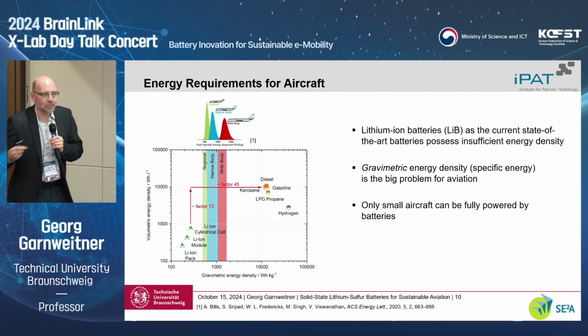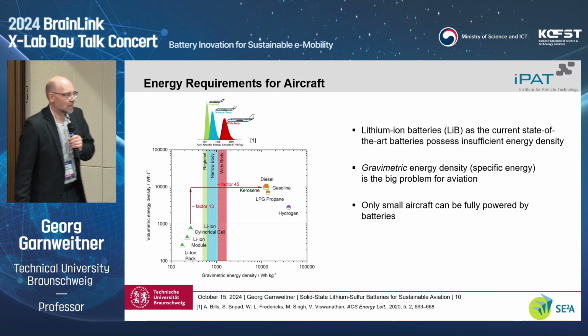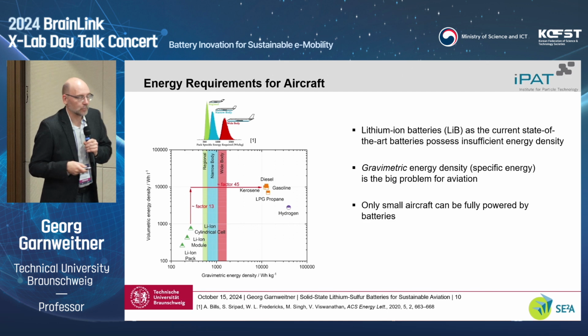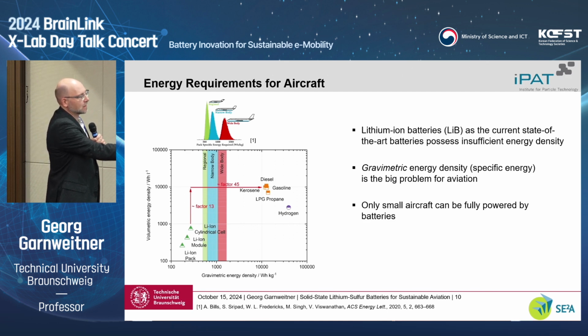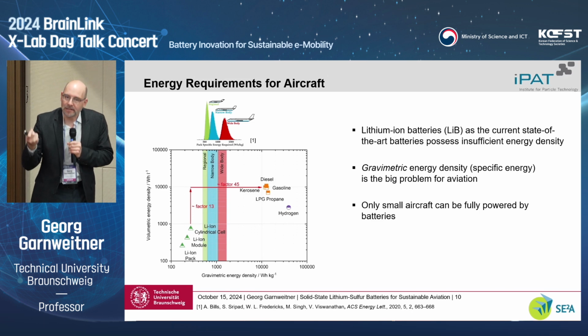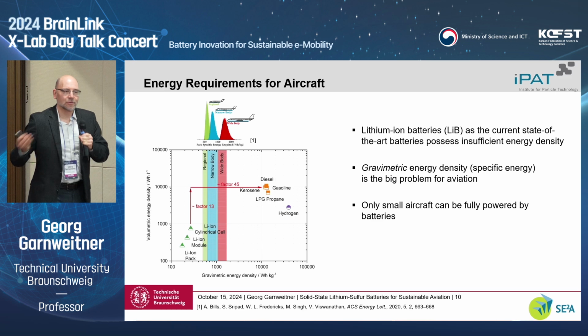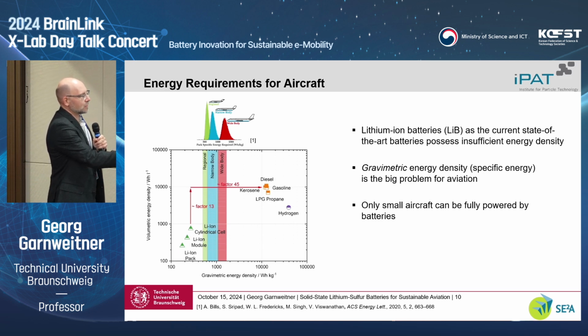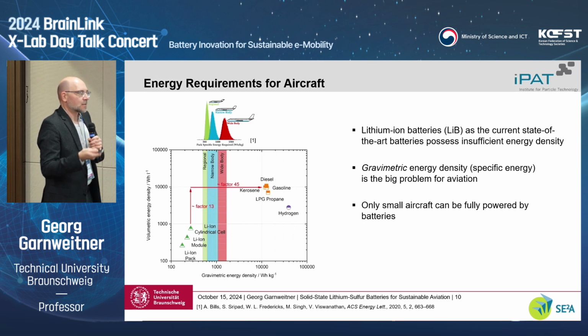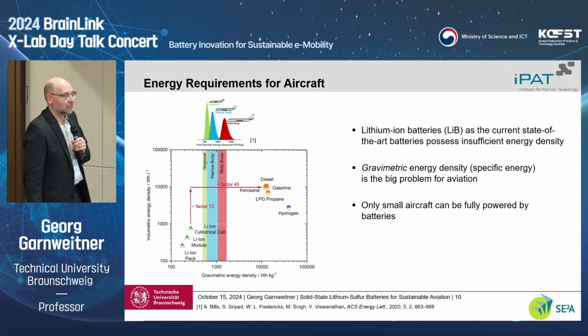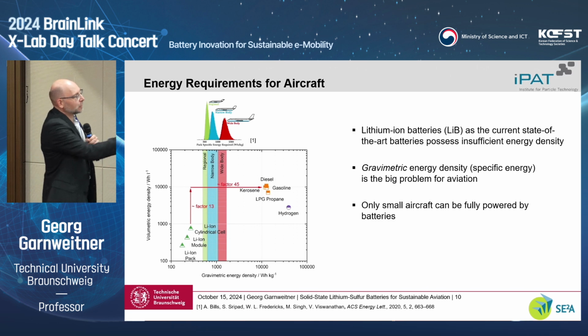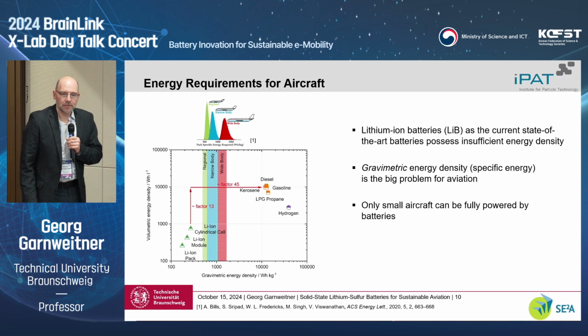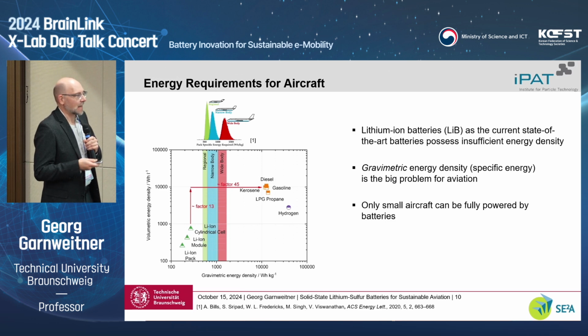It's not fully what we need, because also the efficiency is not 100% for kerosene. But nevertheless, we see that we are not there with the batteries, especially taking into account that often what you find in the literature is a value for cell level. But of course, the battery has to be included in a larger module or in a pack, and all of these additional components, they will reduce the energy density. So we will see, or we do see, the lithium-ion battery that we have plotted here does not fulfill what we need for a battery-powered airplane. And if we compare different types, then we see, well, of course, we are closest to a smaller plane, only for a regional application. And this is, let's say, the one that appears realistic today. Nevertheless, we still have a gap that needs to be bridged.